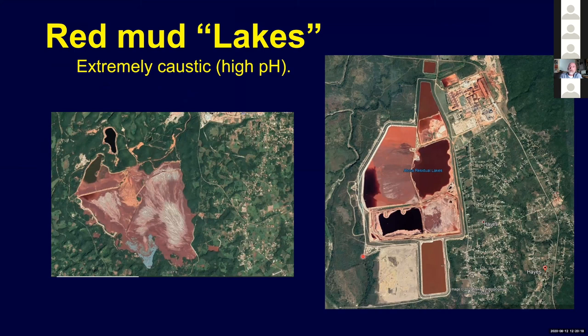There have been a number of experiments and small projects done to see if we can make this material into brick, for example. But most of the time, the costs are much too high to do that. So they sit. You may recall in Hungary, about 10 years ago, one of these dams that you see that contained this material failed, and the red mud came down the hill and flooded into the Danube. It was quite an environmental disaster.